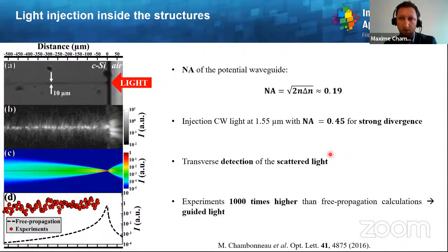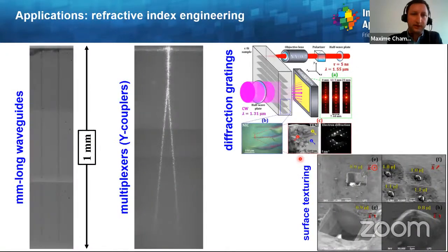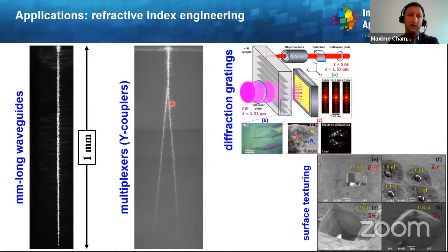Then with this positive refractive index change, it is possible to find some applications in the field of refractive index engineering for writing millimeter-long waveguides, as you can see here on the left, multiplexers for splitting and coupling the light, also called Y-couplers. We have inscribed diffraction gratings, and also we have performed surface texturing, either with negative index change or the positive index change corresponding to the waveguides, where we see some micro pyramids on the surface of silicon after selective chemical etching.